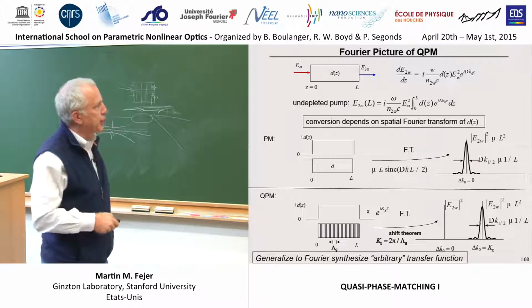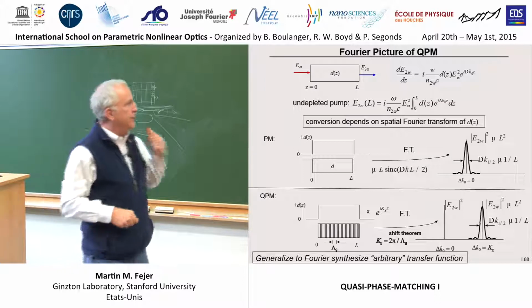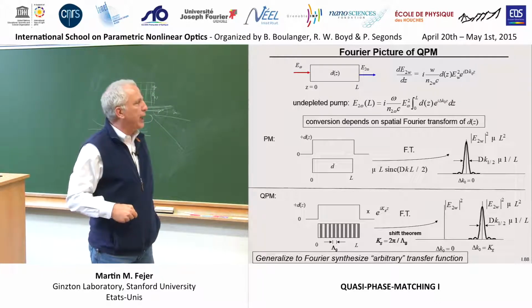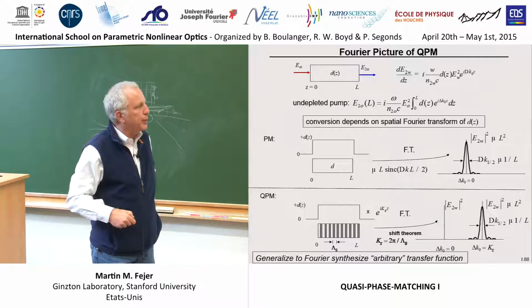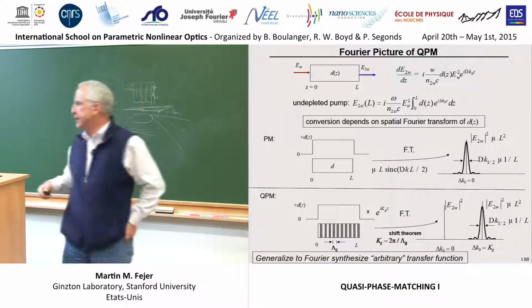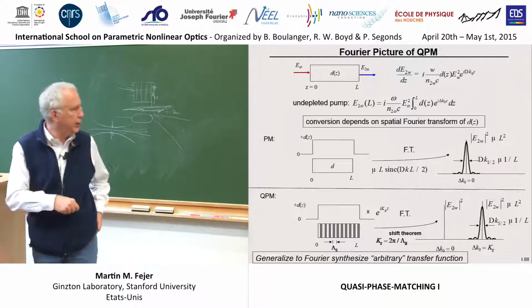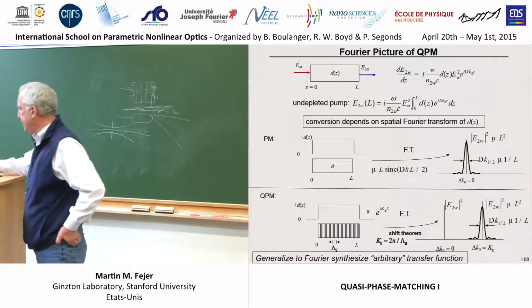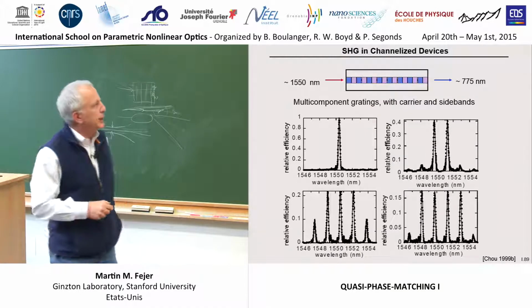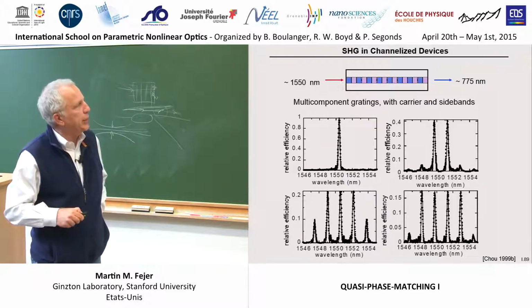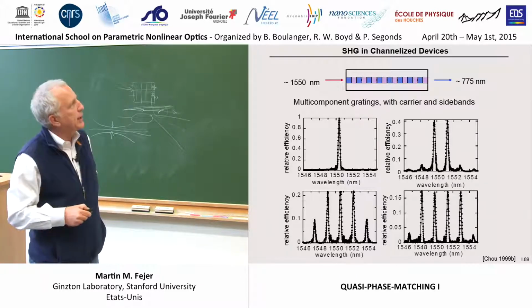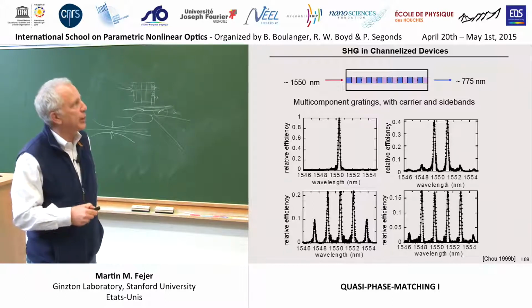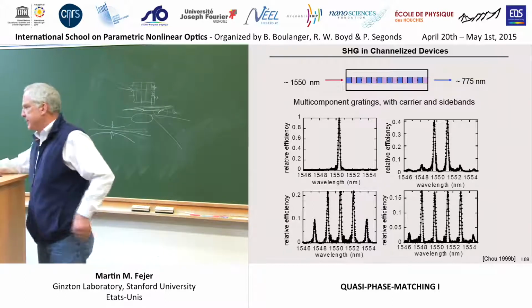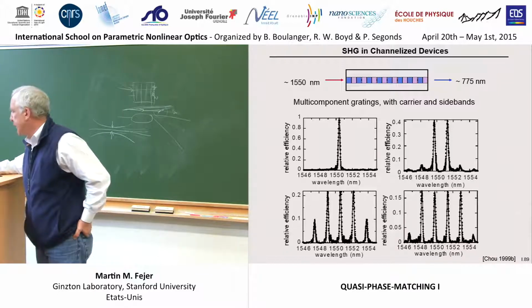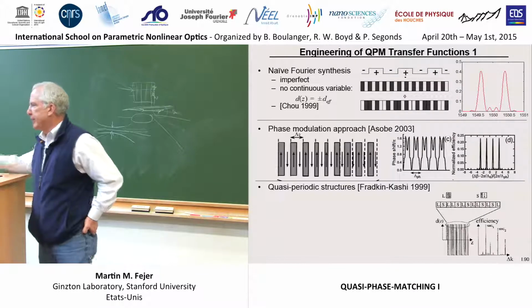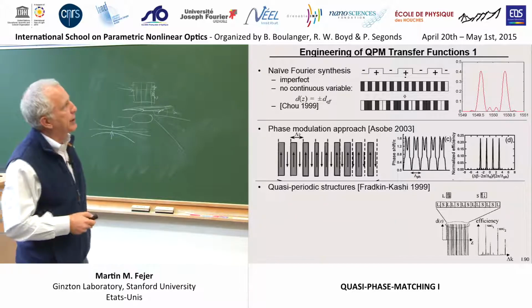This was our simple picture of a simple periodic structure. You could imagine adding other Fourier components to this structure, and instead of having one peak, you could have 2 or 3 or 4 peaks. We'll talk about how you can do this kind of Fourier synthesis in a minute, but just to show you that you can do it, these are tuning curves engineered to have 1 peak or 2 peaks or 3 peaks or 4 peaks by changing this away from a simple periodic structure. This isn't terrifically useful for what we were just talking about, but similar domain engineering can be done to make other kinds of transfer functions.